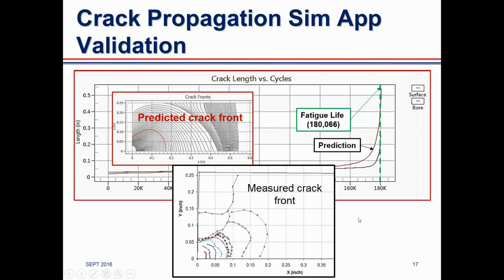And here is a measured crack front shape. What is seen is that the ability of the model to capture the actual shape of the crack is very good. And as you can see, these dots represent stages of crack propagation on the specimen, as measured from the fractographic evidence.